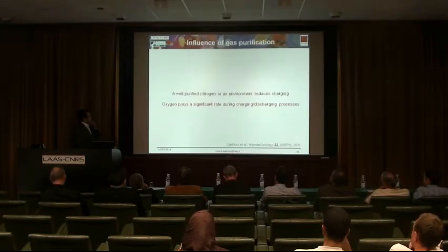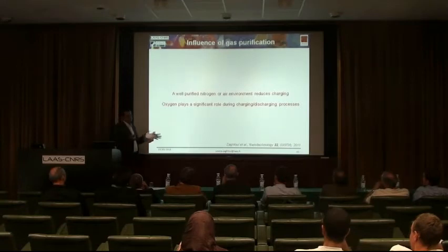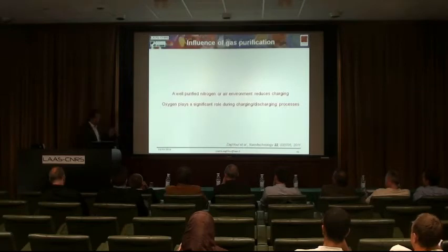Finally, the other important point here is that oxygen plays a very important role in the charging and discharging, and this was the reason for using the oxygen filters. The idea came when we compared nitrogen and air, and found that nitrogen decays faster and has a smaller injected discharge density. The main difference between air and nitrogen composition is oxygen. That's why we purchased this oxygen filter. We put it with a nitrogen line, and in spite of the fact that the amount of oxygen with the nitrogen line is expected to be really small, it has this effect. So this means oxygen is really important. We have to be careful about that.